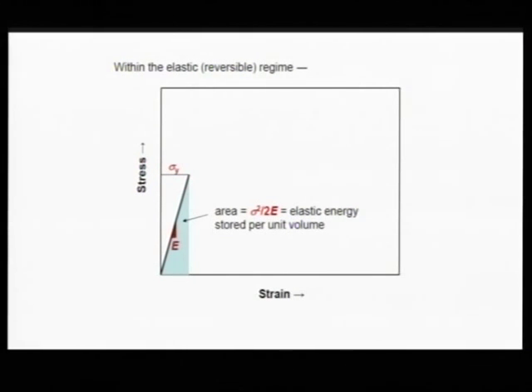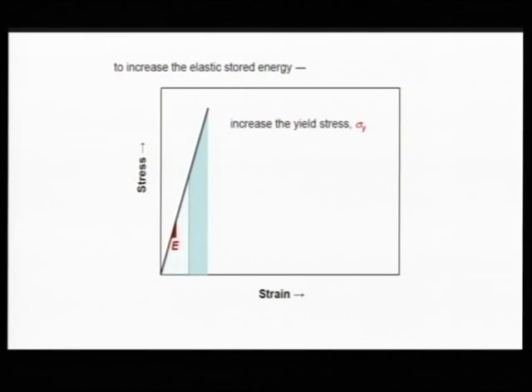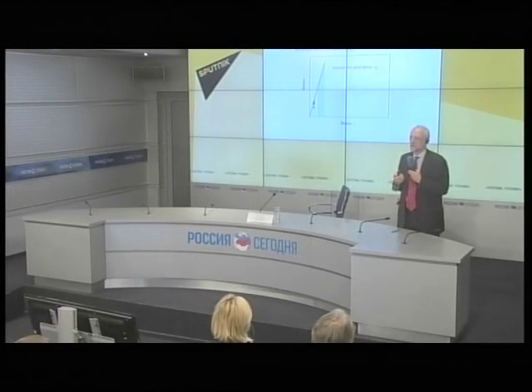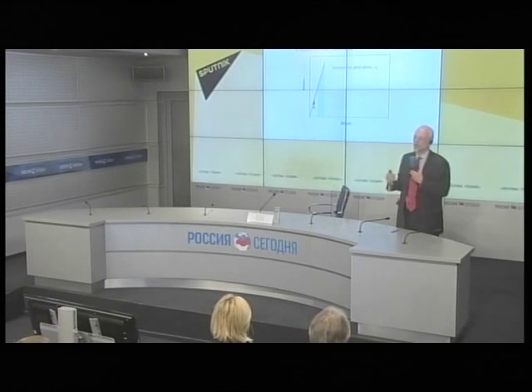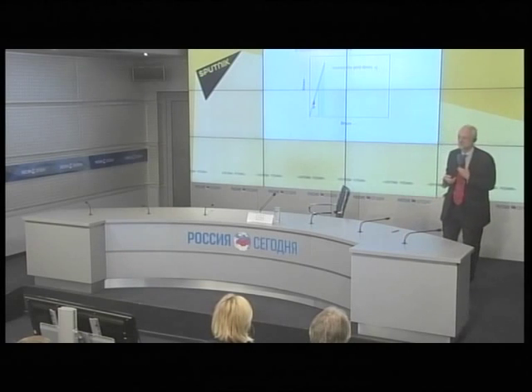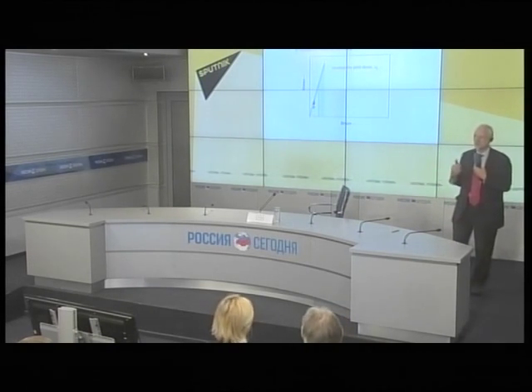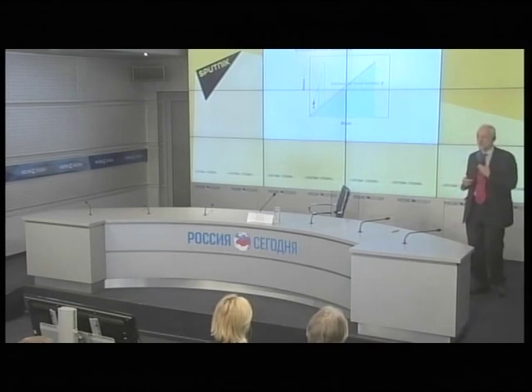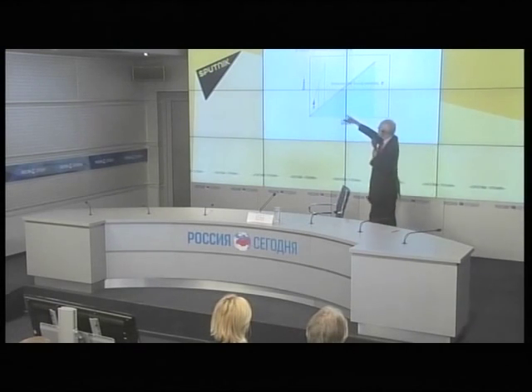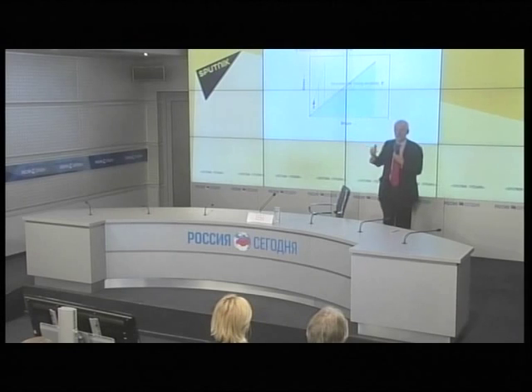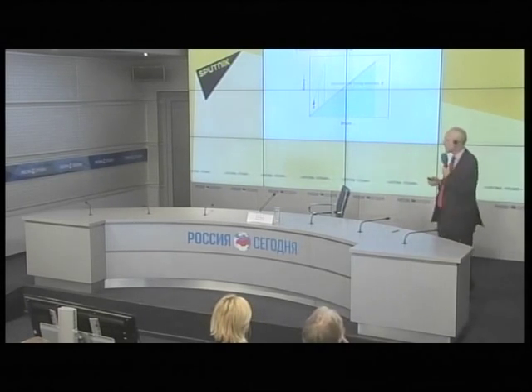So we know what we have to do if we want, like the spider, to maximize that energy. The first thing is you want to make the fibers stronger so you can stretch them further. So we increase the stress. That obviously increases the area of the triangle and the energy. The Young's modulus is more difficult. I think if I approached you with a question about a spring and I asked you if the spring is to store more energy, should you choose a material with a high modulus or a low modulus? Well, the natural answer would be to say high modulus. But actually, what you want is to do the opposite. You want to decrease the modulus, because by lowering the gradient, you of course get a greatly enlarged area, which is the energy.